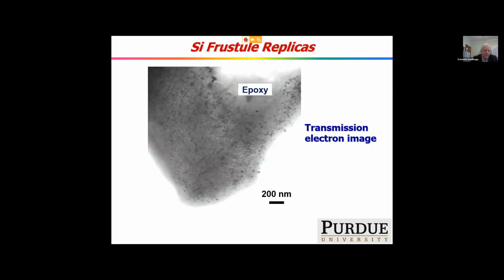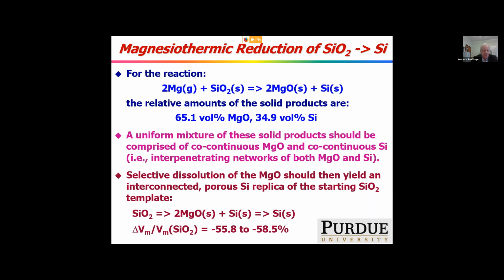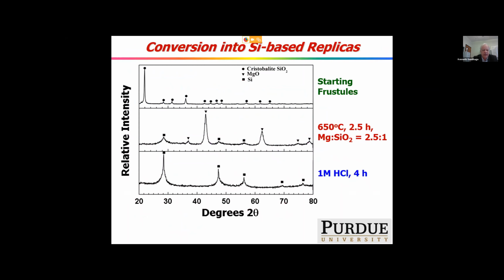Here's a cross-section TEM of a typical nanostructure of these materials, a very nanostructured mixture of MgO and silicon. And so we dissolve the magnesium oxide away in a dilute acid. Magnesium oxide is a very basic ceramic. So we can go from silica to porous silicon because of the volume reduction that happens in this process, typically about 56 to 58% or so. And in doing so, we can generate an all-silicon replica. Again, the peaks are quite broad. If you use a simple Scherrer analysis, it gives you an average crystal size of about 8 nanometers, which is confirmed by TEM as well.